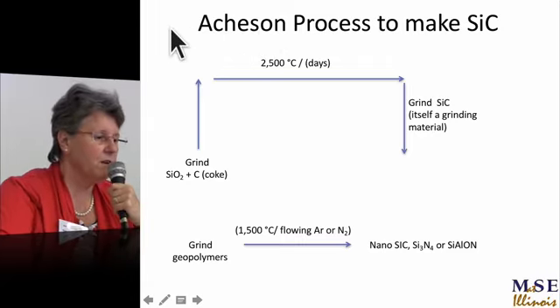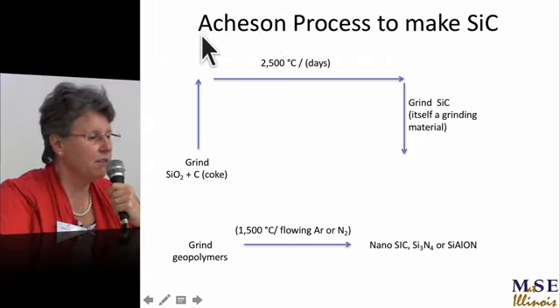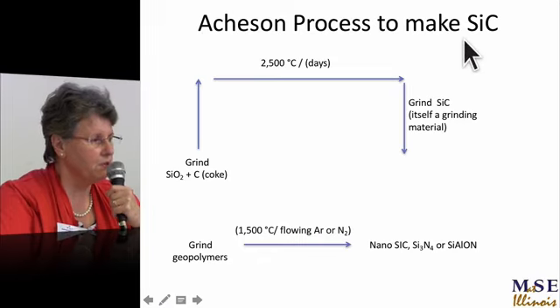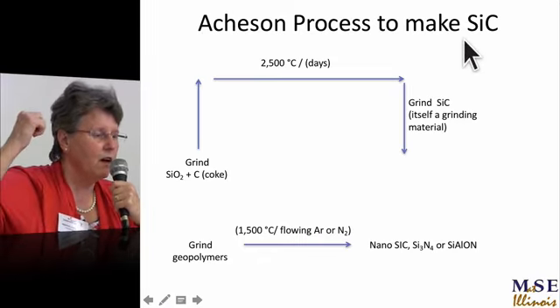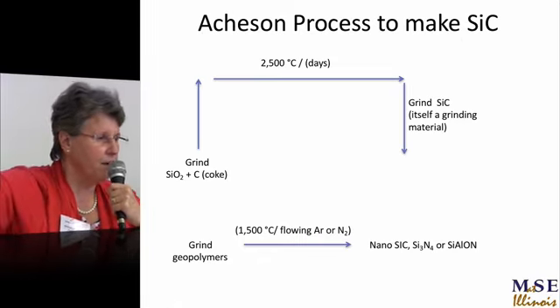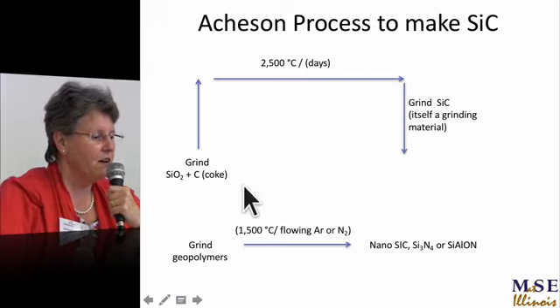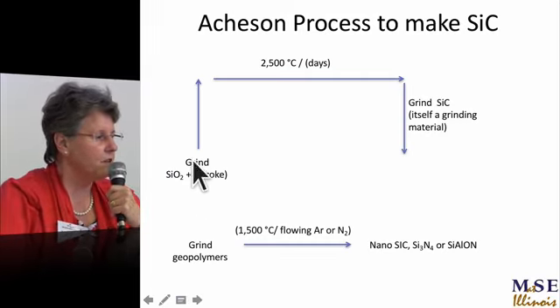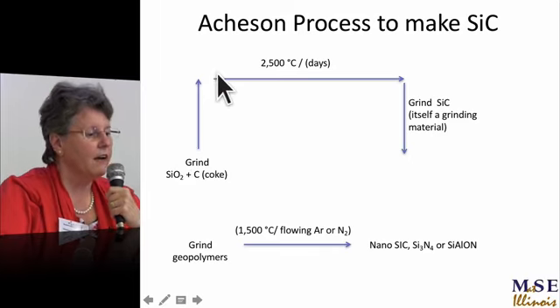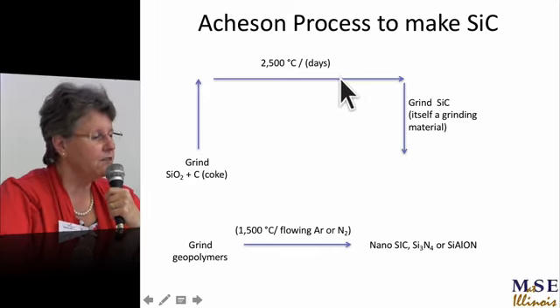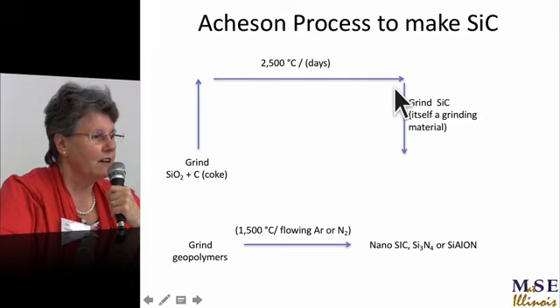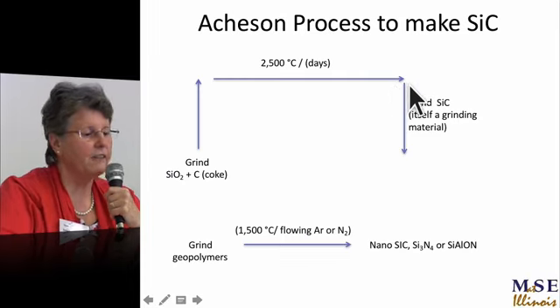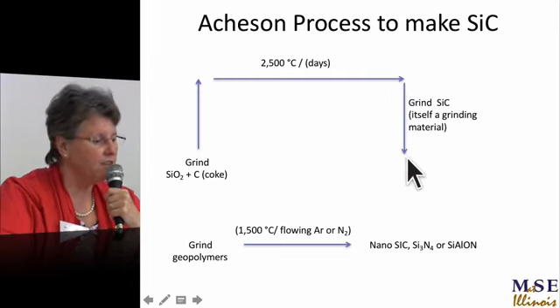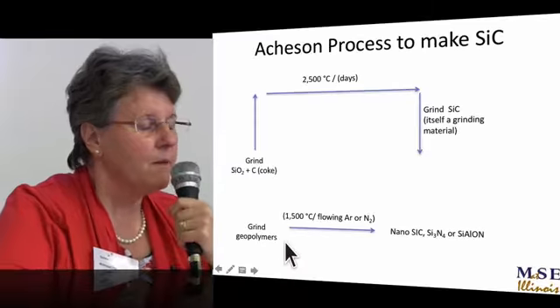So I teach ceramics how to make silicon carbide. You use the Acheson process. You go down to the Bodensee and you get hydroelectric power that costs a fortune, and you get silica and coke and grind and grind and grind, and then you heat to 2,500 degrees C for days, and you make silicon carbide, and then you grind and grind and grind and get some silicon carbide to sell. That's a lot of energy, a lot of energy.